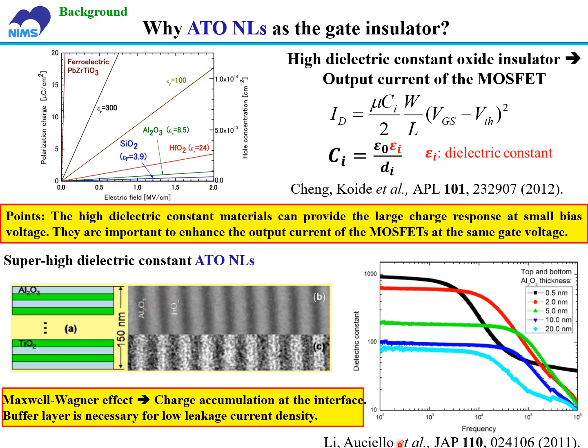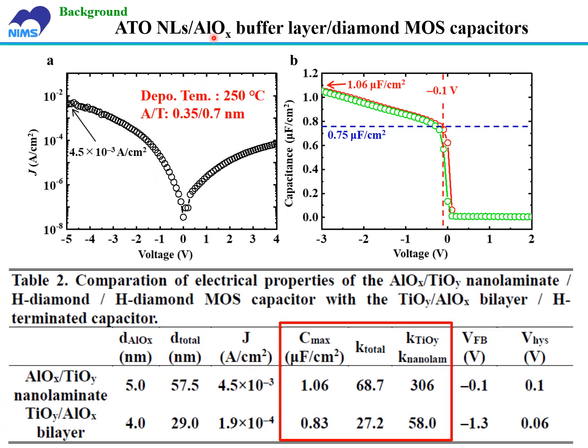Around 20 years ago, Professor Akihiro Ohtomo's group fabricated the super high dielectric constant ATO nanolaminates with a dielectric constant as large as 1,000. Therefore, we can choose this material for the fabrication of electronic devices. We have fabricated ATO nanolaminates, aluminum oxide buffer layer, diamond MOS capacitors, and MOSFETs. The deposition temperature for all of the oxide insulators is 250 degrees C, with a sublayer thickness of 0.35–0.7 nanometer. The total thickness for the oxide insulators is 57.5 nanometers. The maximum capacitance for the nanolaminate is 1.06 microfarad per square centimeter, which is larger than the titanium oxide/aluminum oxide bilayer of 0.83 microfarad per square centimeter.